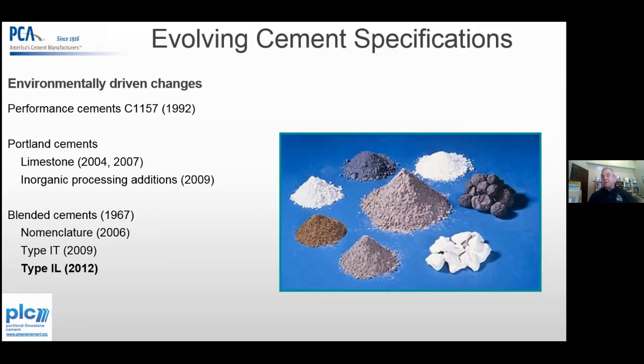other sorts of materials, whether it's organic or inorganic, but just addressing inorganic, you can add up to 5%. So with limestone addition and inorganic processing additions each being at 5%, and your gypsum being approximately 3 to 5, let's just ballpark it at 5, now your clinker factor went from 95 to 85, and it's still not good enough to get where we're going to need to go, unfortunately. And as I said, blended cement has been around for a long time, 1967, so almost 50 years.